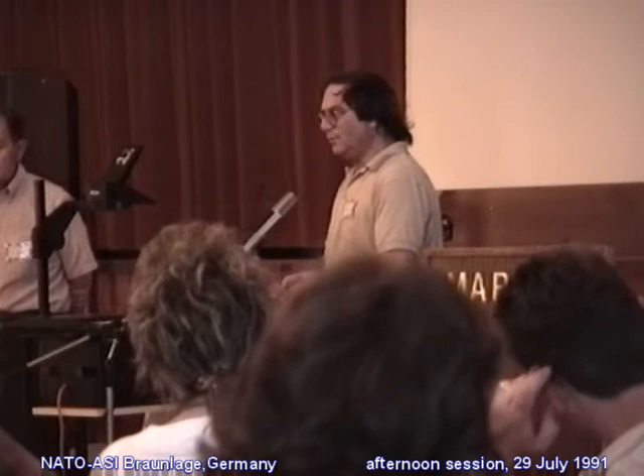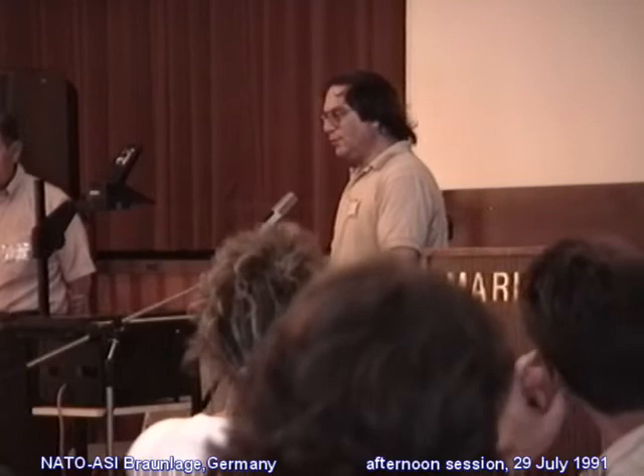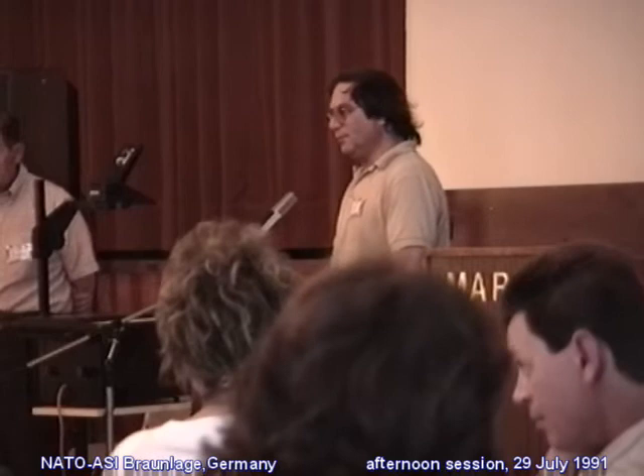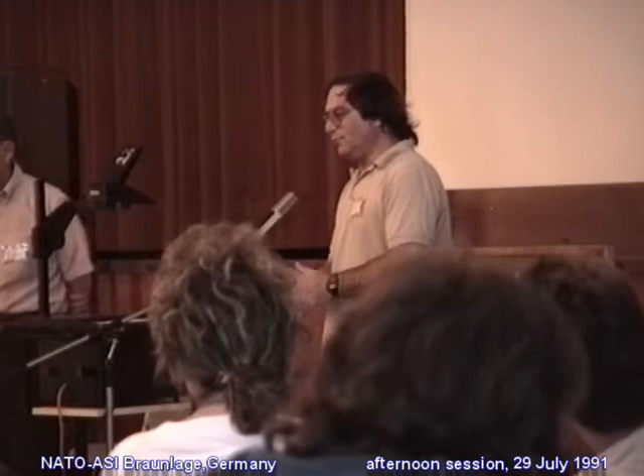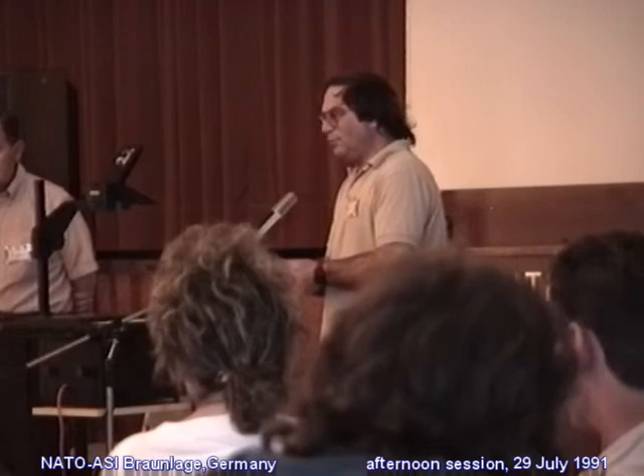And you're at a loss at doing it slowly because you just cannot do it slowly, because it's going to have an instability. In that sense, there's a sort of mechanical instability built into certain systems so that you cannot do it thermodynamically reversibly. And therefore, there may be dissipation occurring in even what one might think of as the most ideal adhesion approach or separation process in practice, which means that adhesion becomes sort of friction in that sense. That's my question.